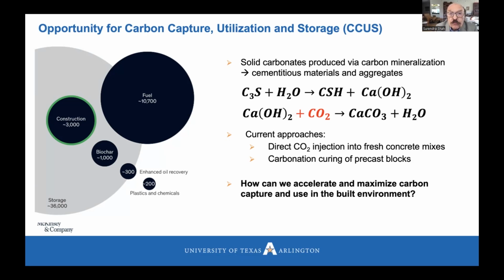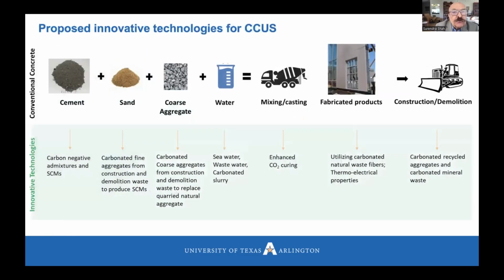So what we must do is to have carbon capture, utilization, and storage in each of the stages of concrete construction. Starting with cement, we should have carbon negative supplementary cementitious materials. Aggregates occupy 70% of concrete, and we can carbonate recycled aggregate to replace natural aggregate and sand. And sand, as you know, is in critically short supply worldwide.